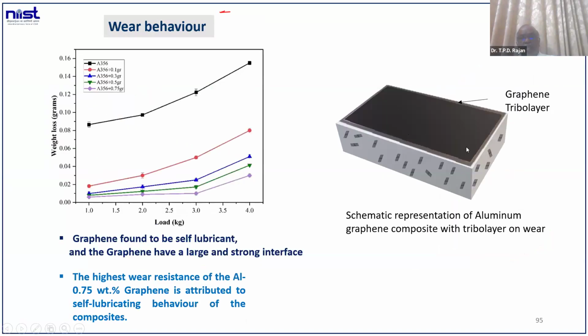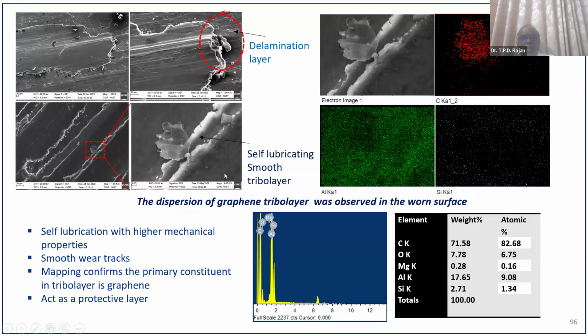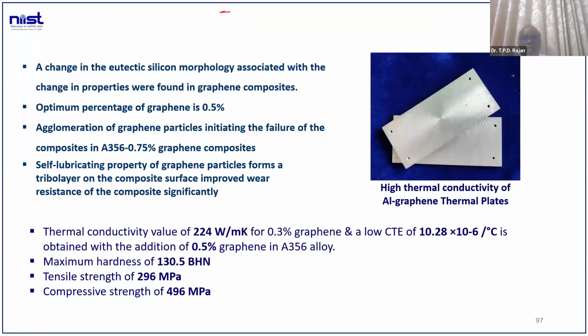And the wear resistance, again, because of the self-lubrication behavior of this graphene, this is the wear loss actually. So the wear loss of the 356 alloy is higher, but once you add the graphene, 0.1 percent, 0.3 percent, 0.5, and then 0.75, it shows that increasing the graphene content, because of the presence of the self-lubricating graphene, the wear resistance is getting increased. And here we can see these are the carbon-rich layers which are found, called a mechanically mixed layer, which will not allow further wear loss. So this will act as a lubrication layer in the composites. So this can be used to make thermal management plates or even the pantographs or any of these things because of the higher thermal and mechanical properties.